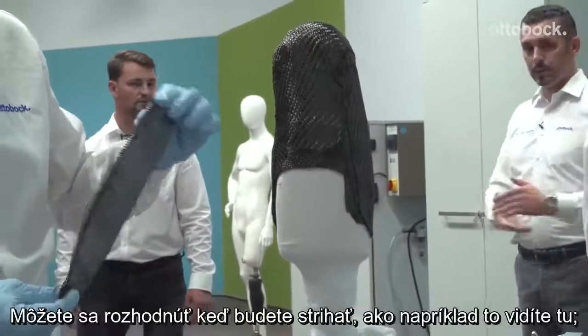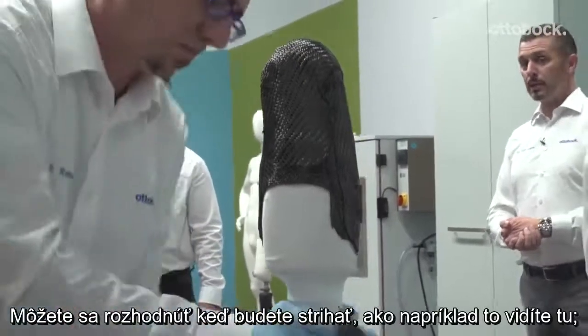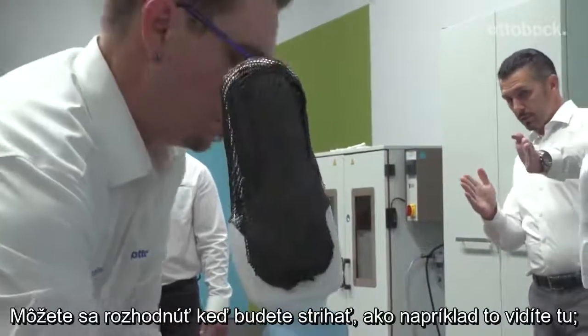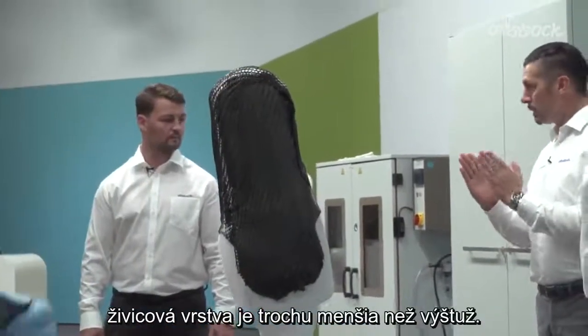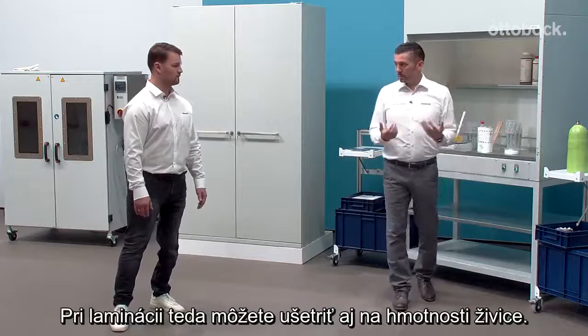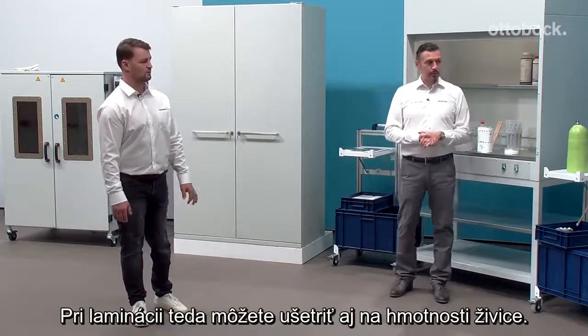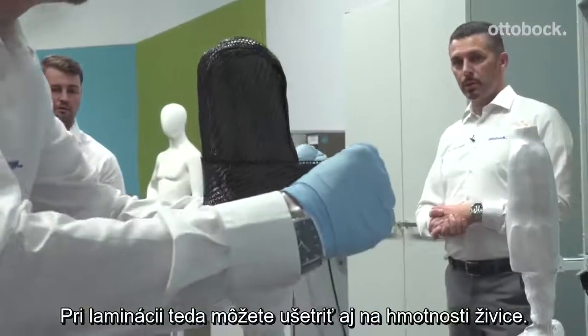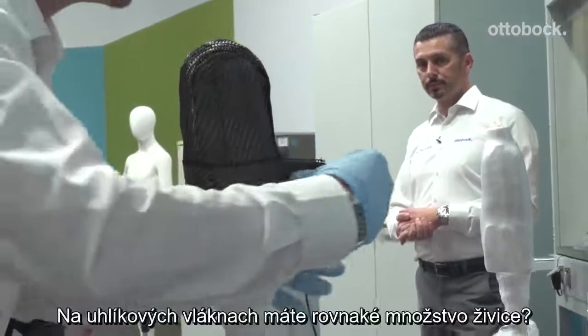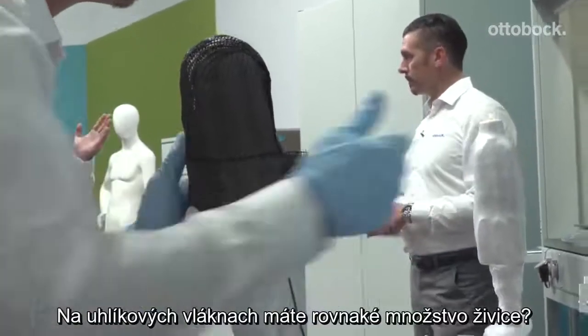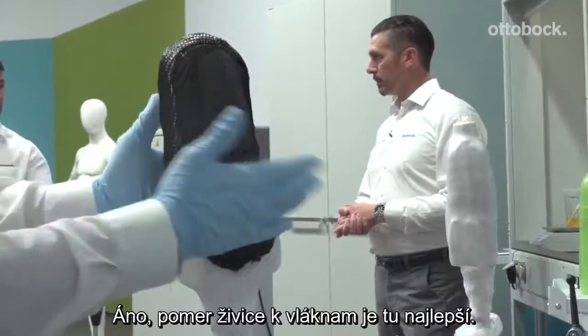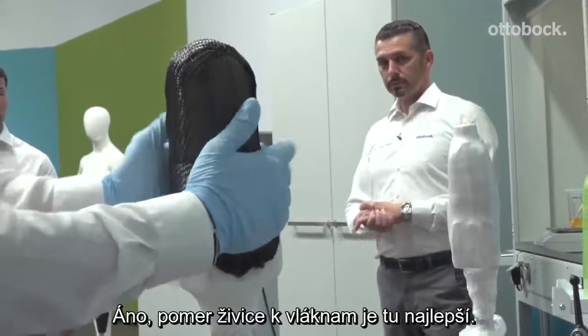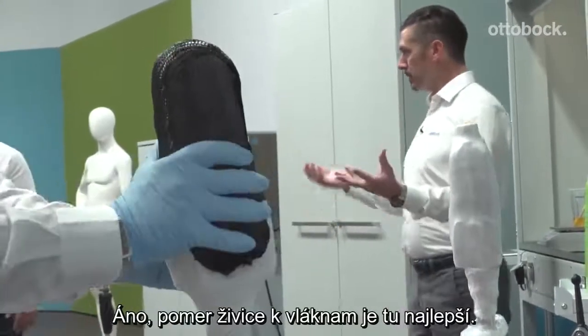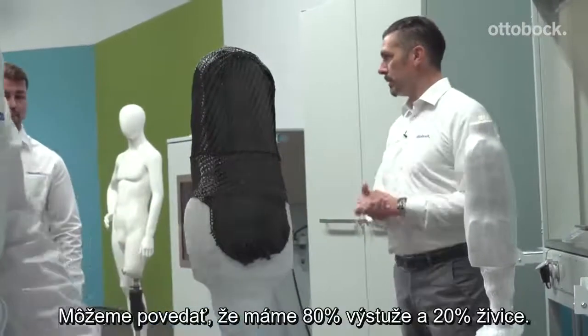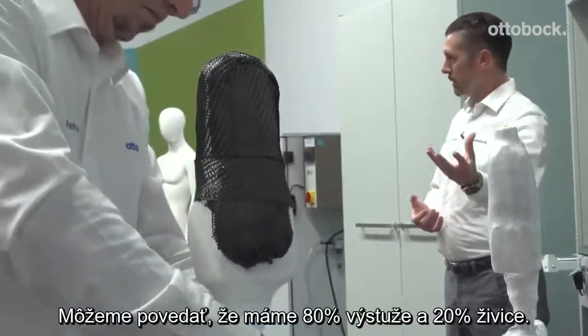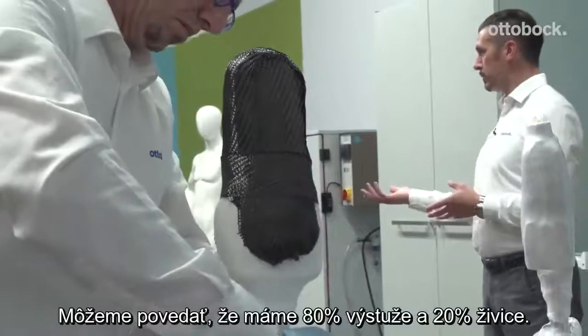With pre-preg it's the same. And you can decide too, when you cut, like you see there, the resin film a little bit smaller than the reinforcement. So you can also save resin weight in the lamination. And you have the same amount of resin on your carbon fiber material? Yeah. So the relation of resin to fibers is the best here. So 80% you can say reinforcement materials, 20% resin.